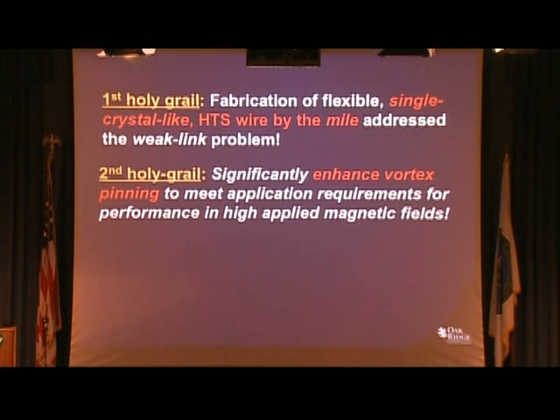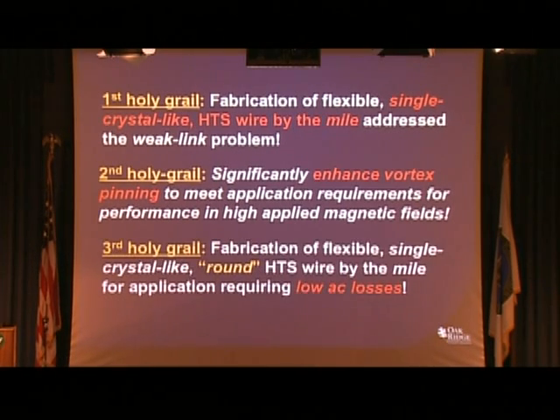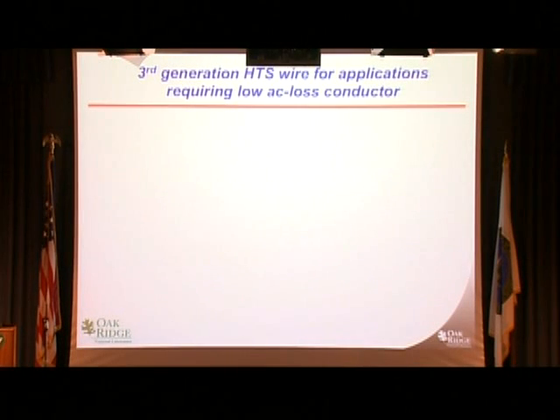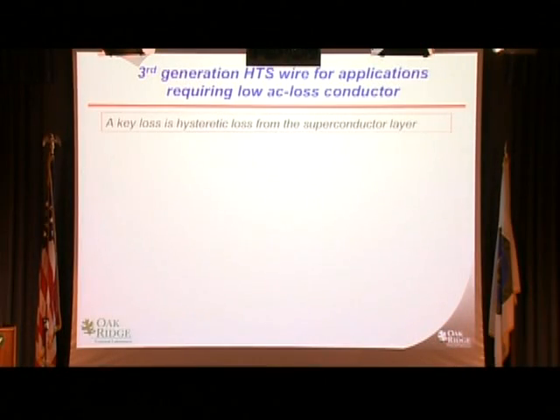So we had the first Holy Grail, then we had the second Holy Grail, and we thought the work was done now. But of course, as I mentioned, there's always more to do. So we quickly learned that there are some applications where AC losses are really quite important. And here's the problem with AC losses. We made this really nice wire, a single crystal-like wire, with nice nanostructures, that carries lots of current and field. What's the problem? Well, in applications where AC losses are important, there's a hysteretic loss that comes from the superconductor layer.